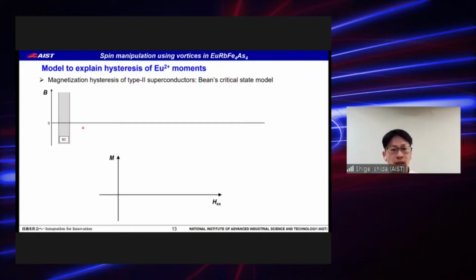When an external field is applied, the field penetrates the superconductor from the surface in the form of vortices. Note that the slope here corresponds to Jc, and the smaller B inside the sample results in negative magnetization.